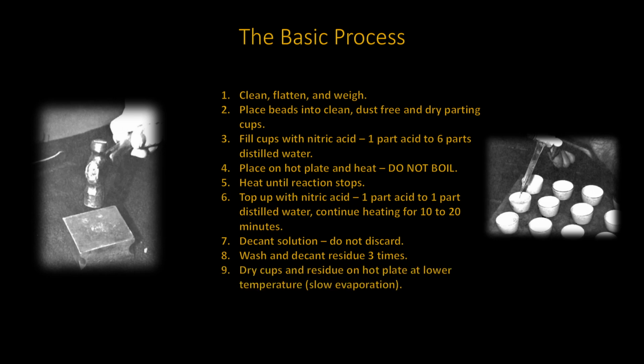Set the cups containing the beads and residue back onto the hot plate. Using a lower temperature, allow the cups and material to dry using a slow evaporation process. The intent is to reduce the possibility of sputtering of the last few drops of water. That may break up the gold bead, which could throw some gold out of the cup.